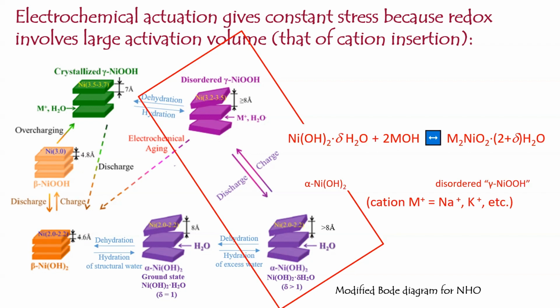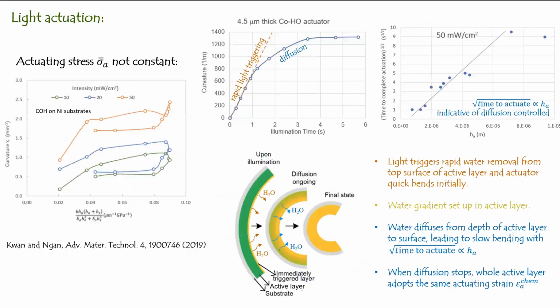So because of the insertion, okay, the activation volume is large. And also the crystal structure changes. And that's why the activation volume is large, and therefore the stress dependence is high. So therefore, the stress is pretty constant.